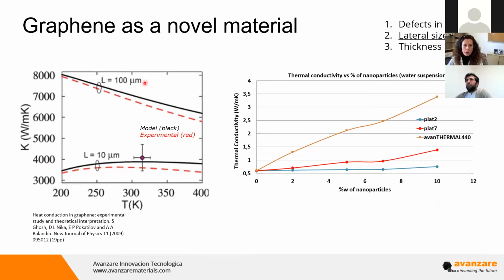For example, if we compare 100 microns lateral size to 10 microns lateral size in the same kind of material, the difference is 2, even 3 times higher, because the higher the lateral size, the easier is the movement of the phonons. Also in experimental results, we can observe that a small platelet of about 2 microns in lateral size barely increases the thermal conductivity, while with a platelet of about 40 microns in lateral size, as we increase the weight percentage of this nanoparticle, the thermal conductivity is increasing significantly, in this case up to 3 watts per meter Kelvin.